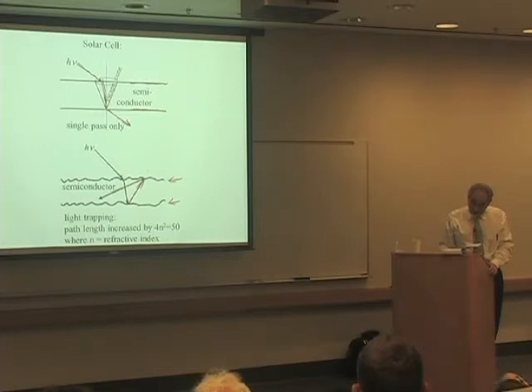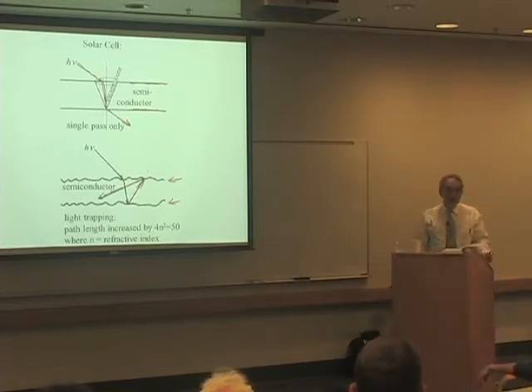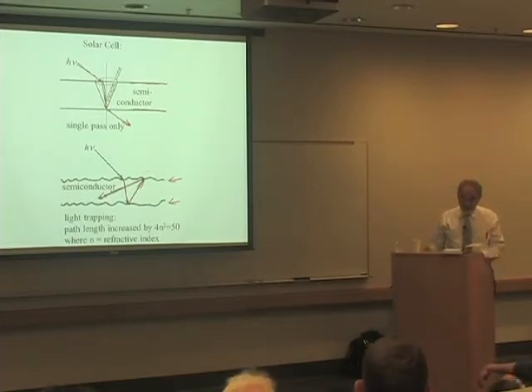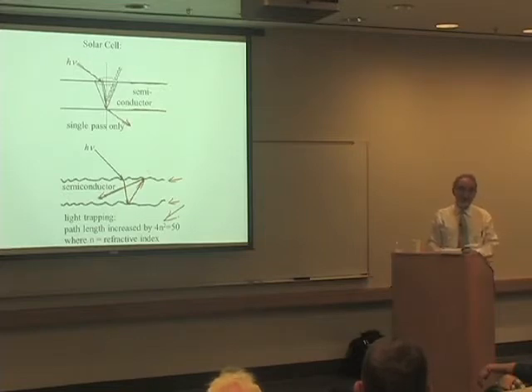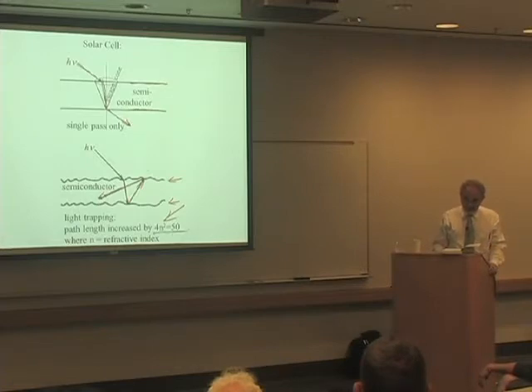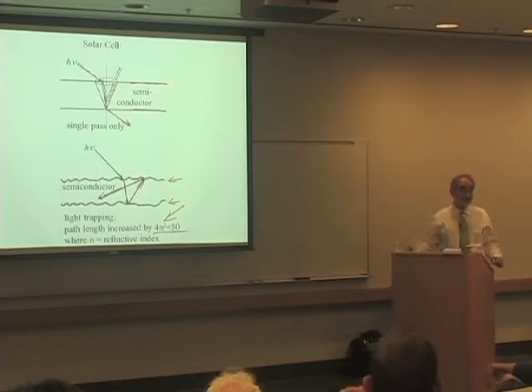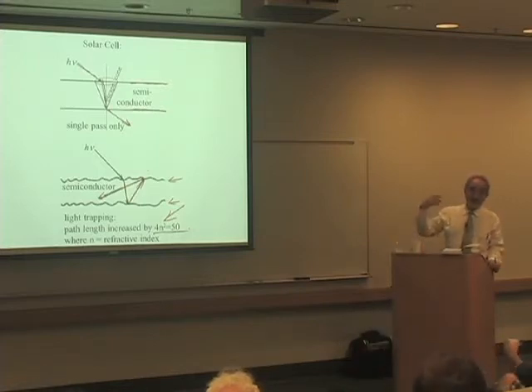And it bounces again. And it bounces many times. And then the internal path length is increased. And if you do a little calculation regarding the increase in the internal path length, it's 4 times refractive index squared. That still sounds, oh, that's a number of order of magnitude unity. Well, not quite, because index squared, 3.5 squared is 12, times 4, it's roughly 50. So the path length is increased by a huge amount. This means that you can make your semiconductors 50 times thinner, use 50 times less expensive material, absorb more light,